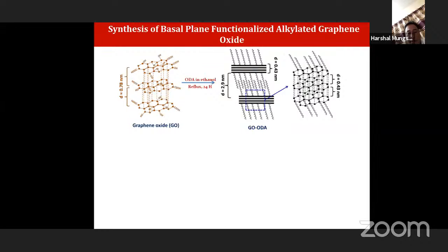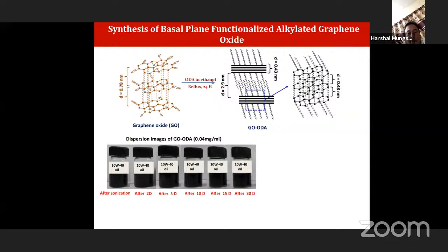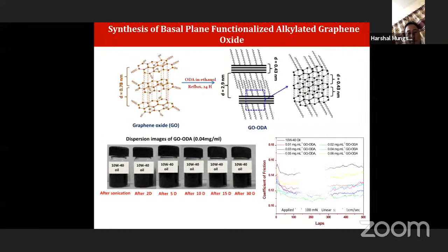Because of this long alkyl chain, it is easily dispersible in the lube base oil. In this case I have used 10W40 lube base oil, and then I checked the tribological properties. You can see the black line is for only 10W40 oil, that is the friction. But when I added this functionalized material to the neat oil, what happened? The friction is reduced. You can see as compared to the black line, the other colorful lines show a reduction in the friction.